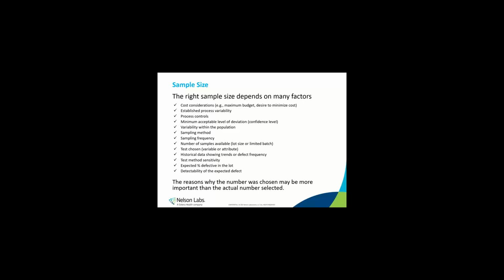Sometimes you're limited on the number of available samples. Maybe your lot size is small, or the samples are part of a small group that has been real-time aged. The test you choose also makes a difference. Data, which includes a measurement, can be statistically evaluated to see how much variability there is in the set. This goes back to variability within the population. And you may be able to decrease your sample size and/or testing frequency if you have historical data showing that the process has been under control for a long time.